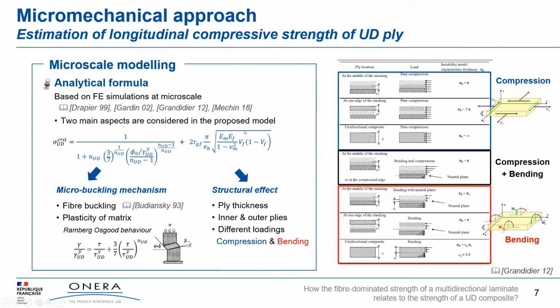In fact, in this equation, the key point is the thickness of the ply, in which you already obtain fiber buckling. And this thickness is going to depend on the applied loading. As you can see, it is different if you apply compression or bending, and it is different if you consider also different position of the 0 degree ply in the stacking sequences, especially if the 0 degree ply are inner or outer plies. So in the next two slides, I'm going to present you the prediction of the model and